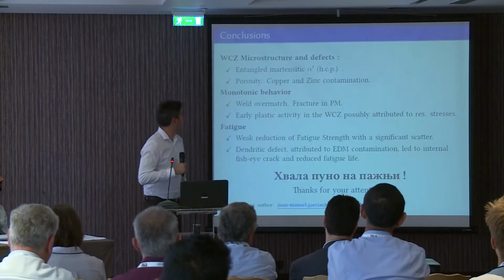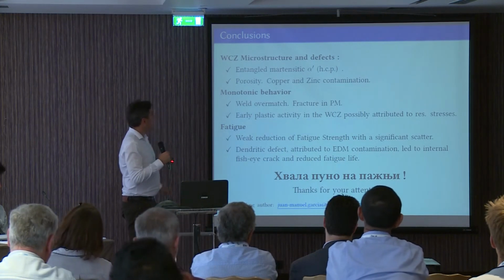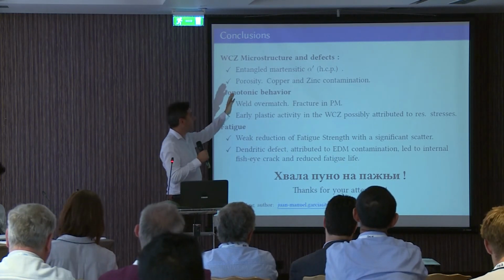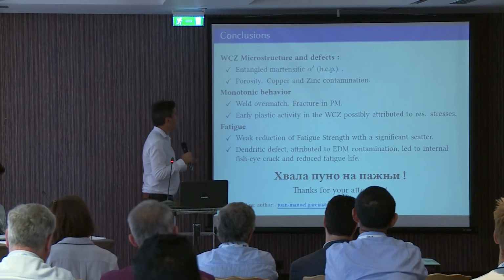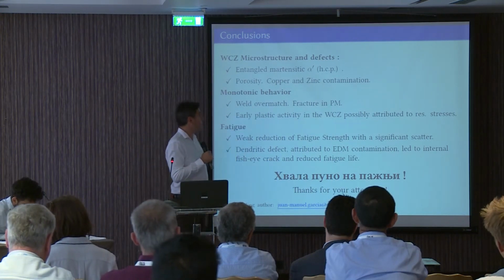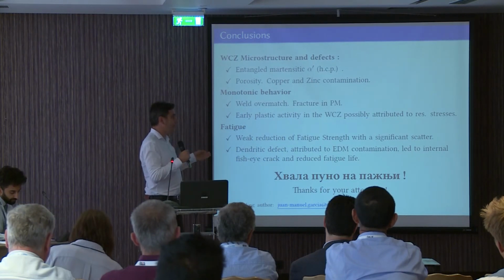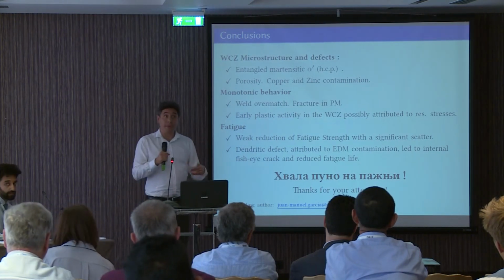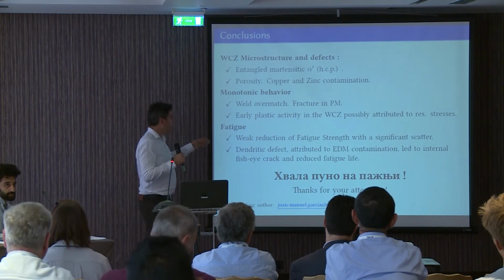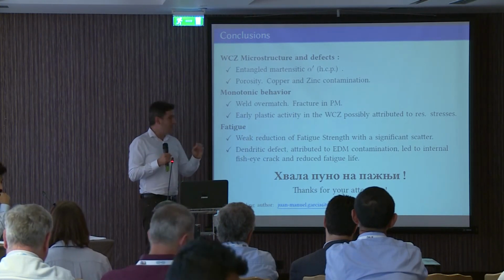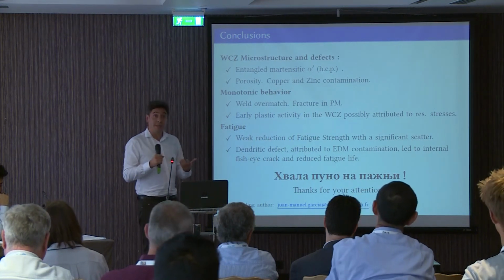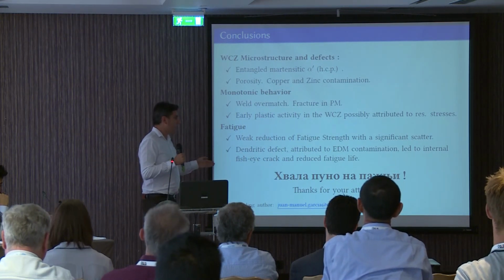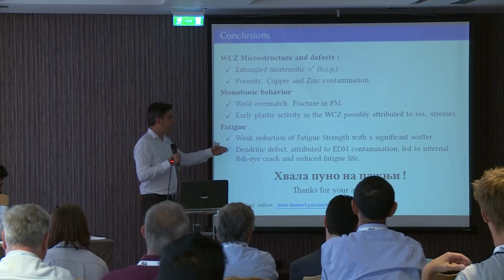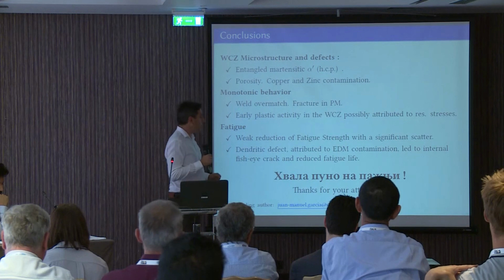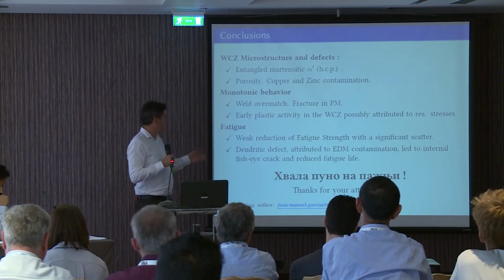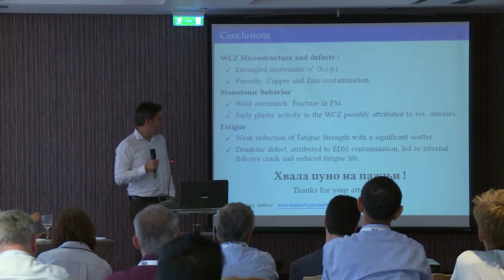So to sum up, we have characterized the microstructure. We have found some defects like porosity, copper and zinc contamination. We have a weld overmatch, and fracture takes place in the parent material. We have plastic activity in the weld center zone, which is probably attributed to residual stresses. And for fatigue, we have found a slight reduction of fatigue strength with a significant scatter. This reduced life was attributed to a contamination prior to welding that led to an internal fisheye crack.